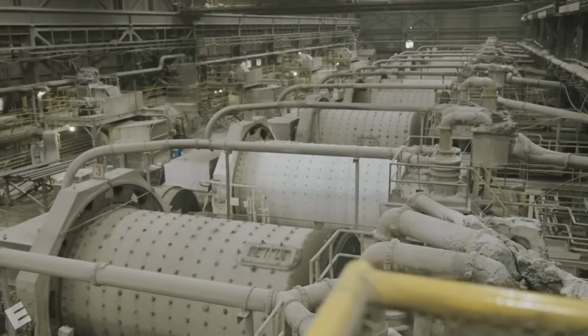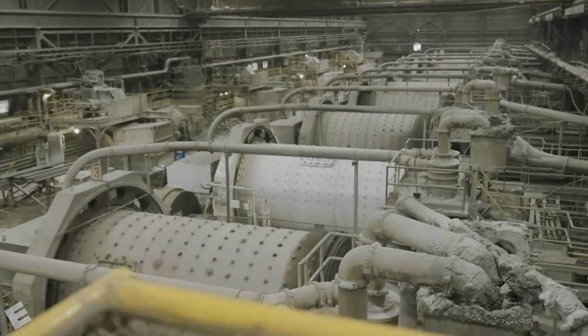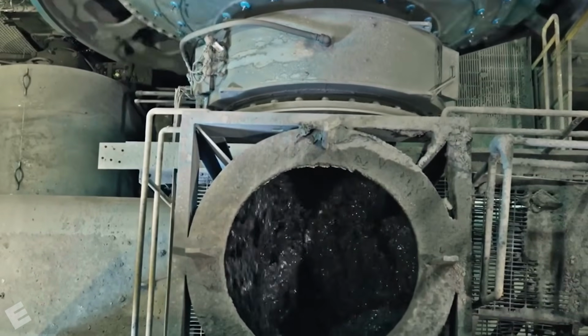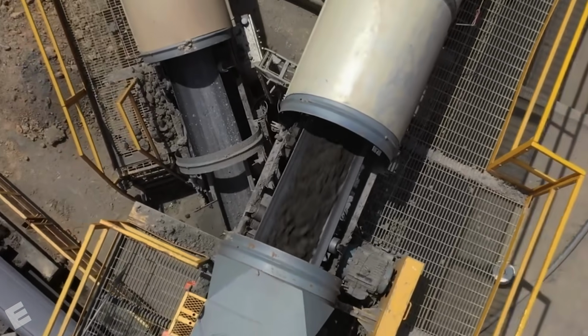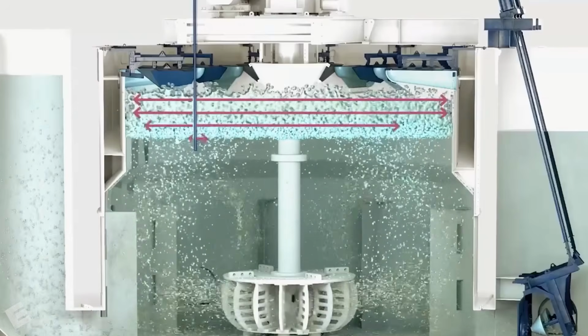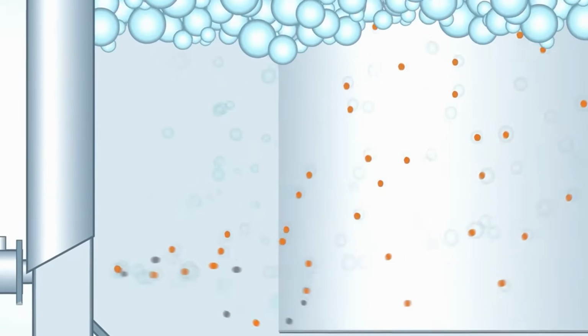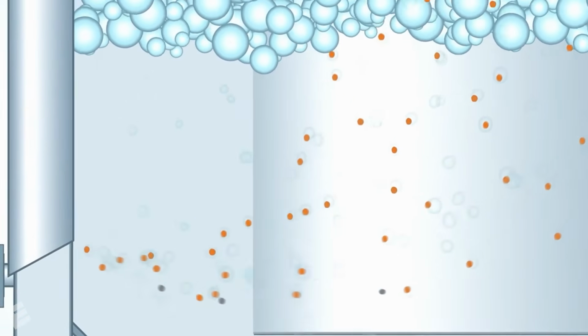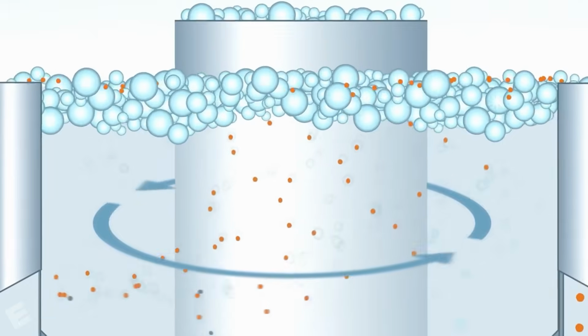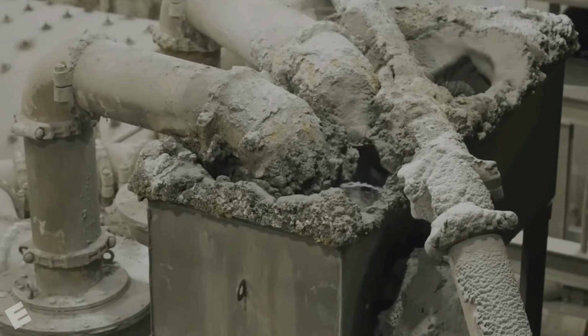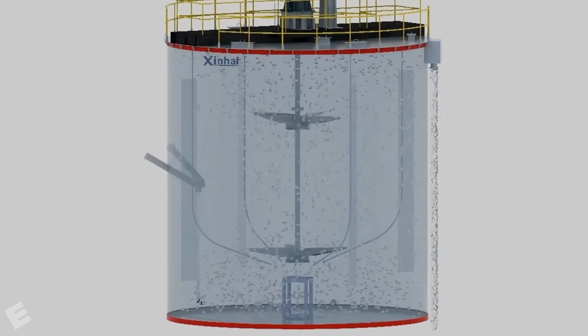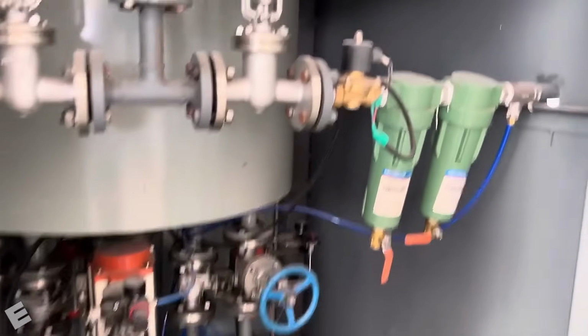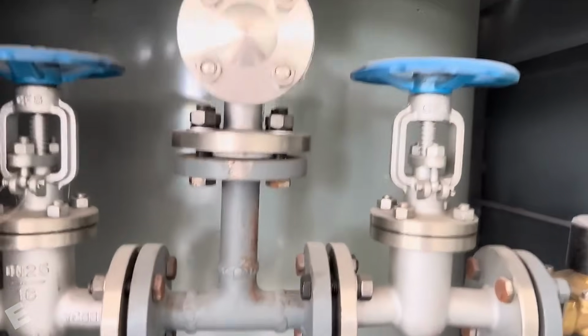The ore is first crushed into a very fine material. Breaking it into smaller particles increases the surface area and allows the silver to come into greater contact with the chemical solution. The crushed ore is then mixed with a diluted solution of sodium cyanide or potassium cyanide. This solution dissolves the silver and creates a soluble compound known as silver cyanide. Oxygen is introduced to accelerate the chemical reaction and improve the efficiency of the extraction process.